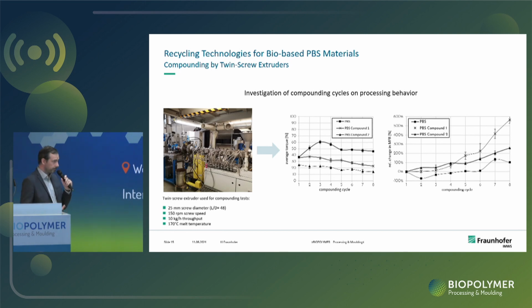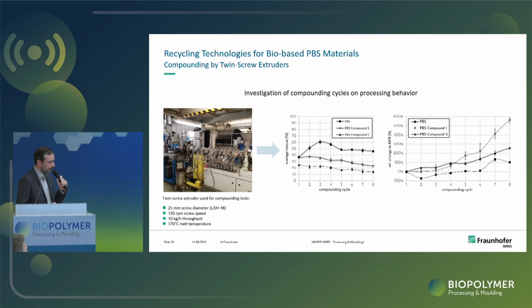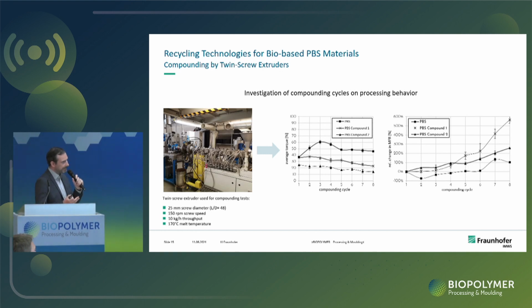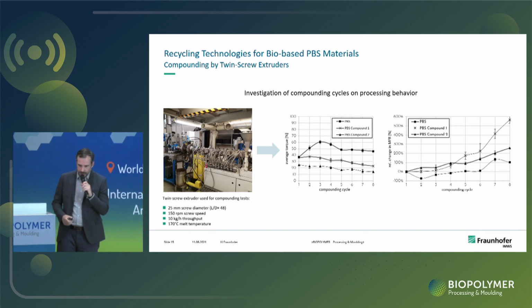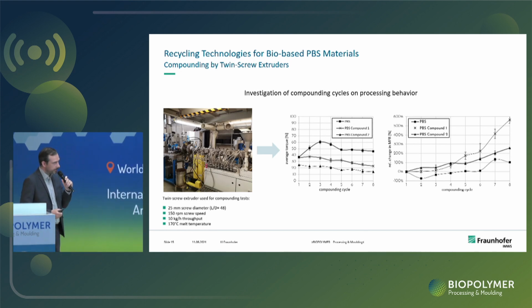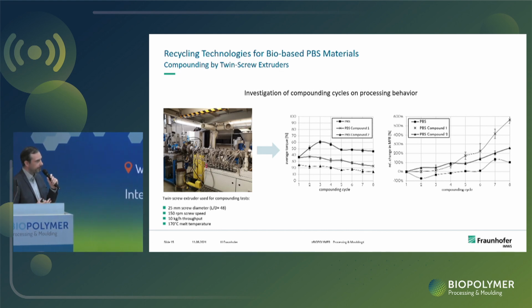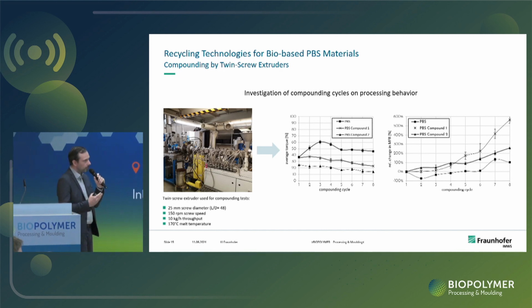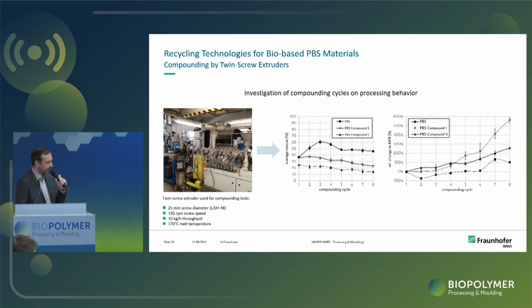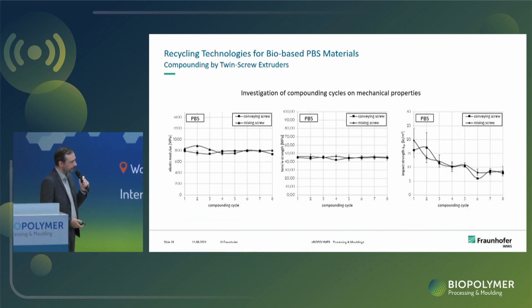reprocessing generates polymer degradation, so that the torque goes down, and at the same time, you can see that the flowability increased. On the right diagram, the MFR or melt flow rate is shown. With more recycling steps, you see that this value goes up, meaning viscosity goes down. And this is also a clear sign that a reduction in molecular weight happens during this recycling or reprocessing.